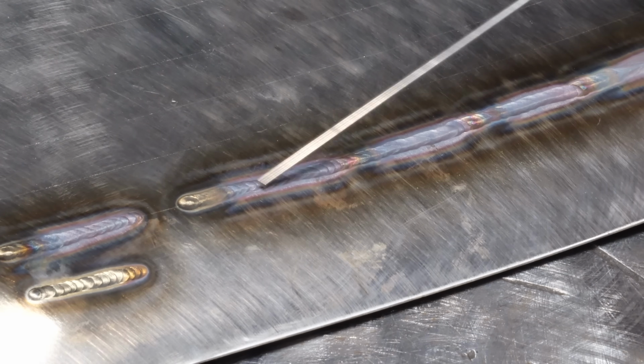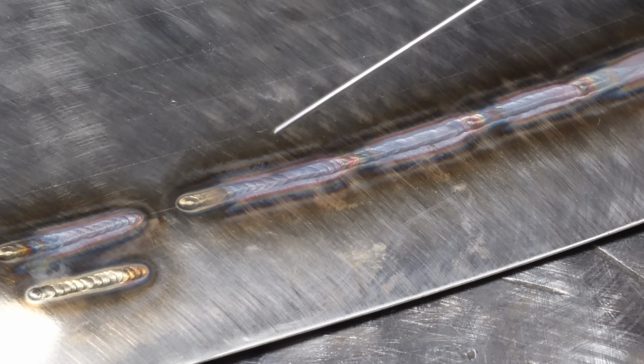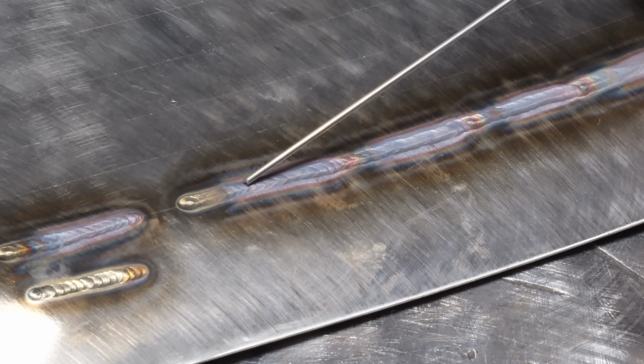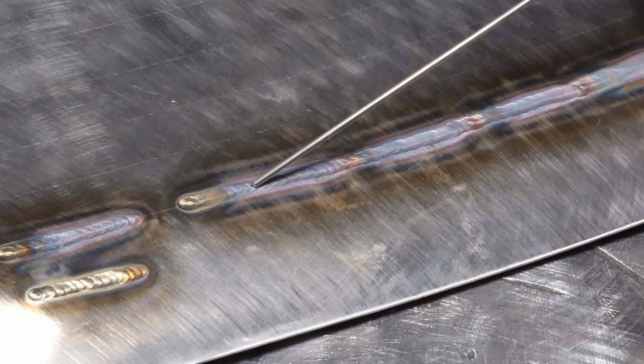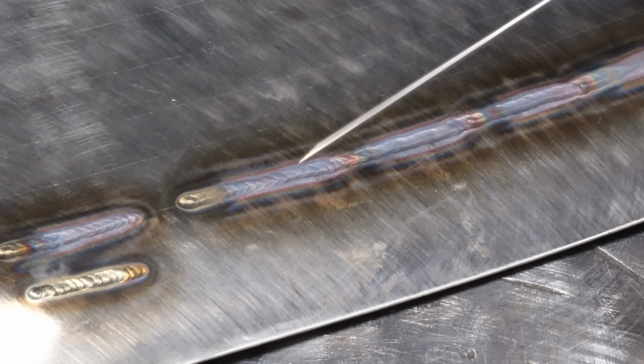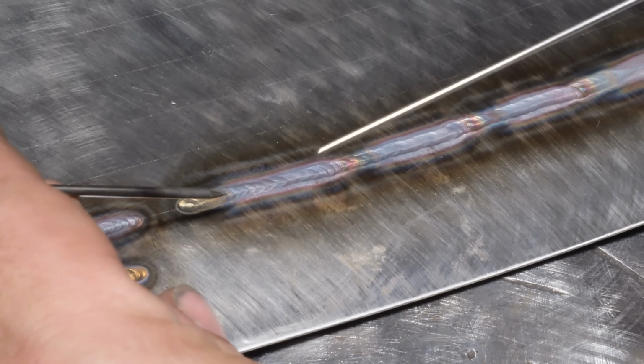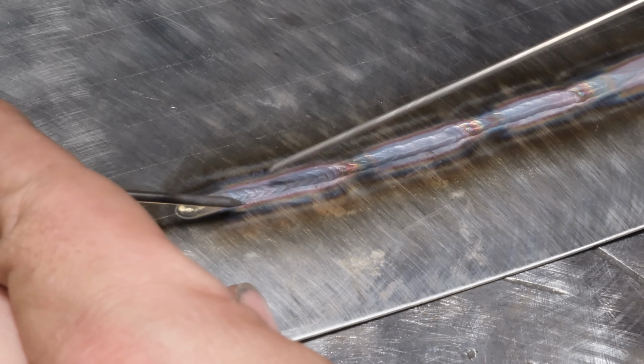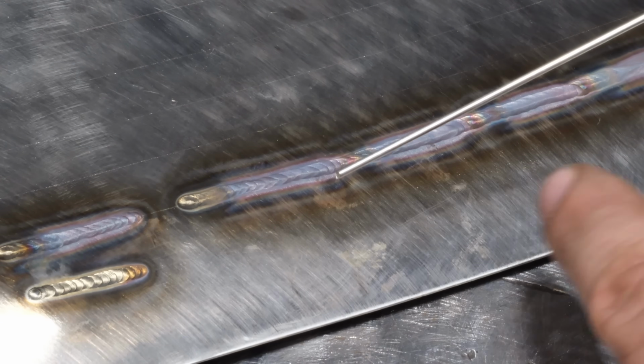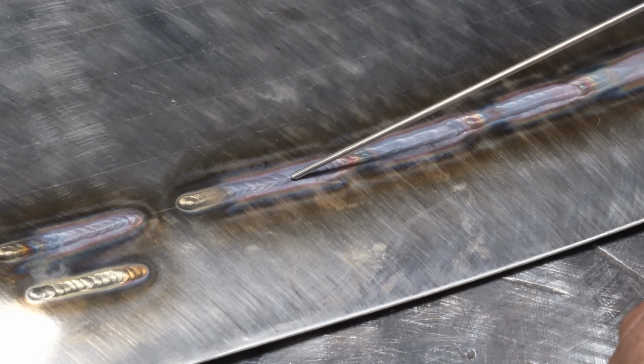Also, you want to keep your filler rod in the argon shielding. It's a very bad habit with this material, and even worse with titanium and other more reactive metals, to dab with your filler, you've got your tungsten here, and you pull this way out of the molten pool where the gas coverage isn't on this. What'll happen is this will oxidize, and that oxide will wind up in your molten pool every time you dab it. So keep that filler rod right in the gas coverage.